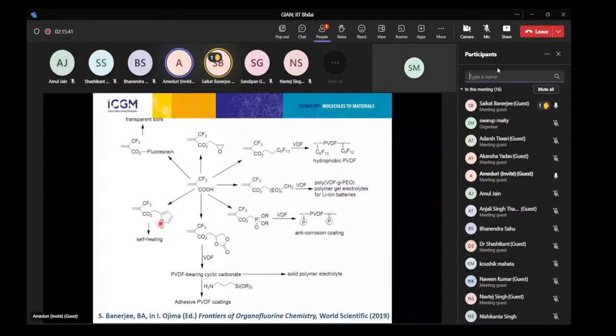But I maintain the temperature with the cooling, the chilled line, controlling it at 45 to 50 degrees, right? I think you have to look at the content of the elastomer. Do you have some VDF in the elastomer? Yes, VDF is in the elastomer, the terpolymer. So what happens is you are going to get a reaction of the phenate O minus onto VDF.